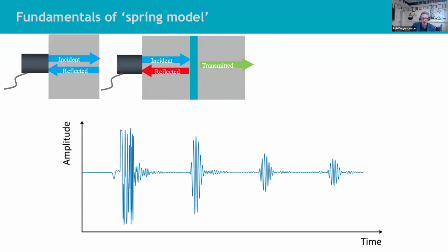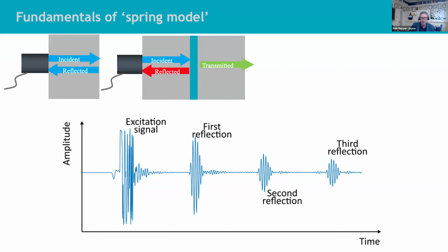If the oil film was really thick, you could detect those two reflections in space, and from the speed of sound in oil, you could work out the thickness of the oil film. But of course, those oil films are really thin. So what you get actually is just one reflection from this interface. So we don't separate it out in space. We separate it out in the frequency domain.